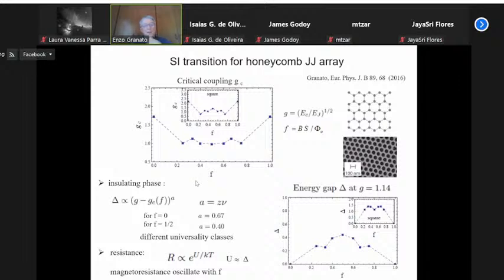Okay. So in the insulating phase, the energy gap vanishes as we approach the critical temperature, and you can calculate the critical exponents. One finds that for zero field, or zero frustration, the exponent is different from 1/2, showing that they are in different universality classes.